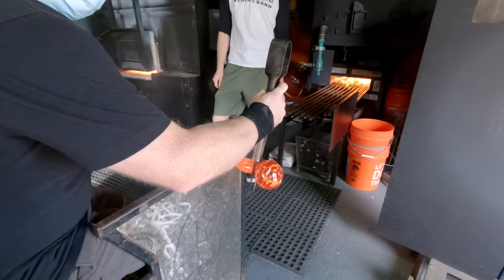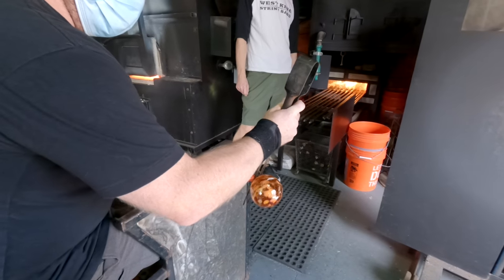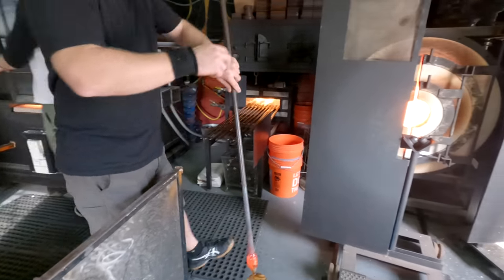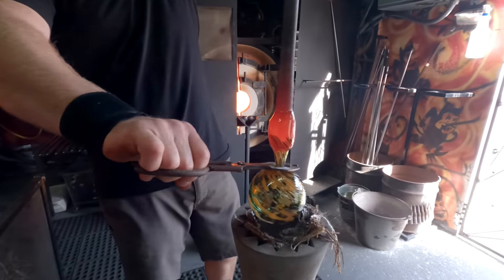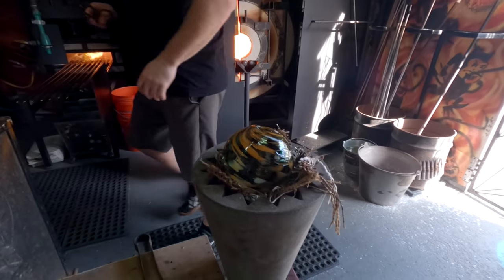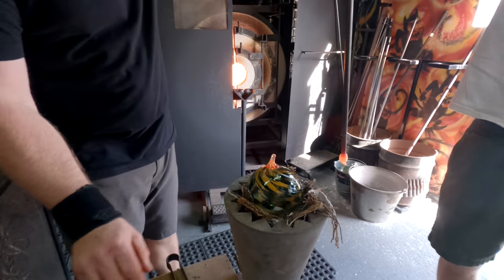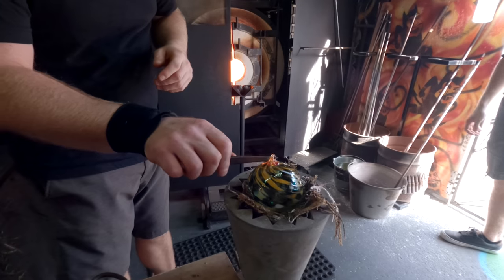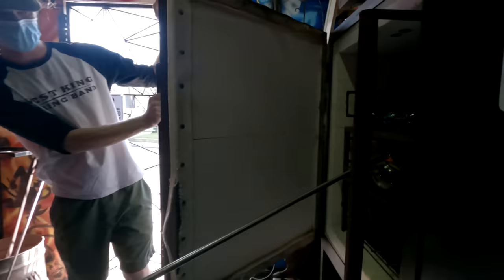There you go — stop for a second, go ahead, and stop. Go ahead and take the mouthpiece off the end, and head back to that safety area. Now we're going to cut the ornament off — the colors are going to change, the orange will change into lime. I'm just blowing it so it doesn't pull up too badly when I lift it, then it's going to go into our annealing oven — it's 915 degrees in there and it has to sit and cool down slowly overnight. There you go — it's an ornament! That's awesome.